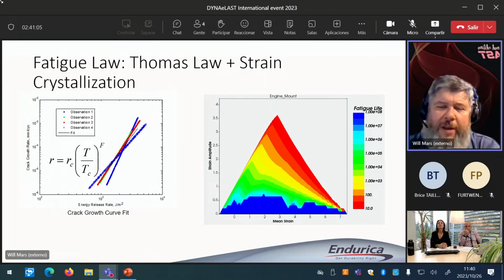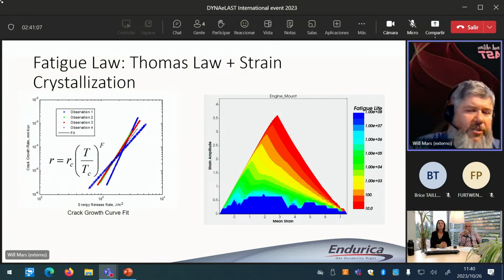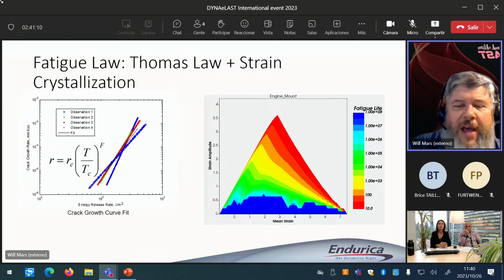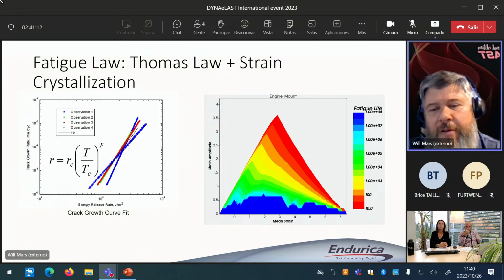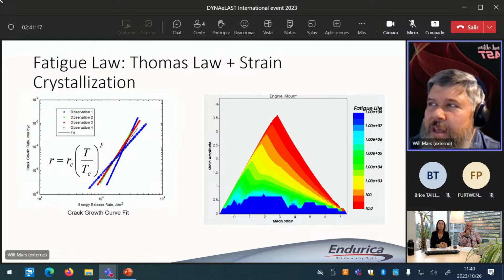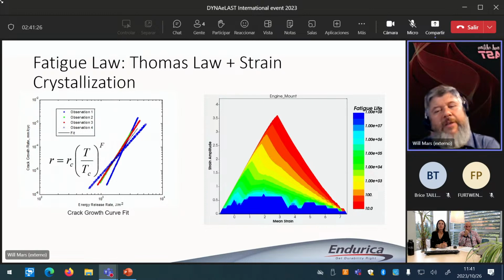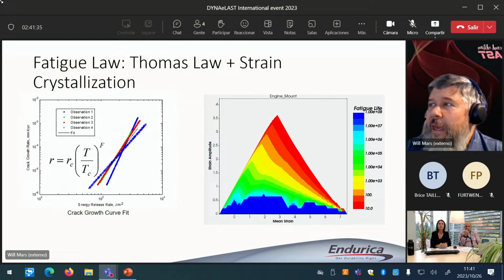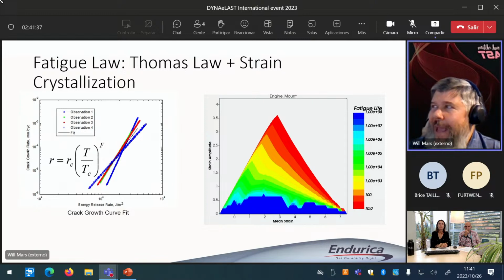Now, in addition to stress strain behavior, if we're going to do fatigue analysis, we need to specify the fatigue properties of the material. So what you're looking at in this slide is an example of the fatigue crack growth rate curve on the left. It's a plot of the crack growth rate as a function of the energy input, just like the Metravib folks were talking about in the last talk. And on the right, you're seeing what's called a Haigh diagram.